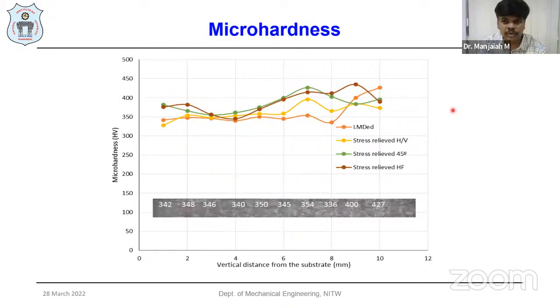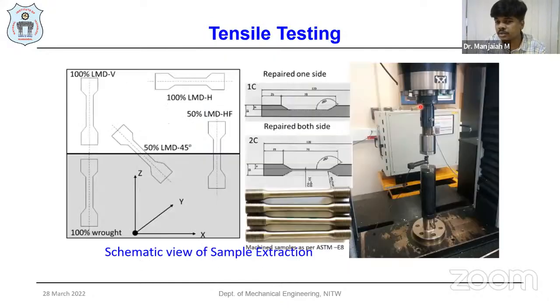And when we measured the microhardness properties compared with the plate manufactured with wrought alloys as well as stress relieved, with the stress relieving we can get better hardness properties and minimize the porosities and all.